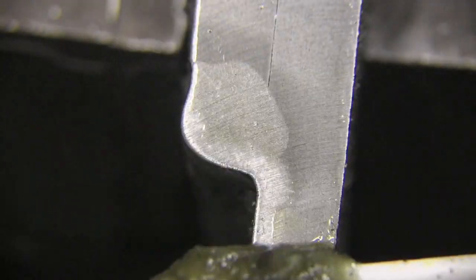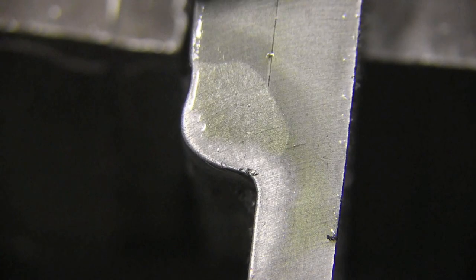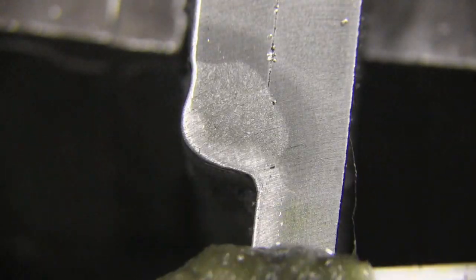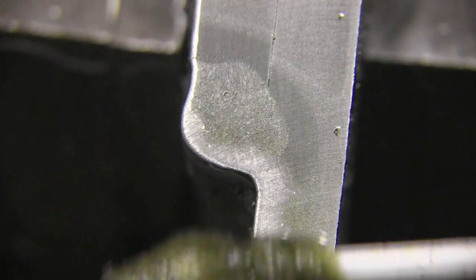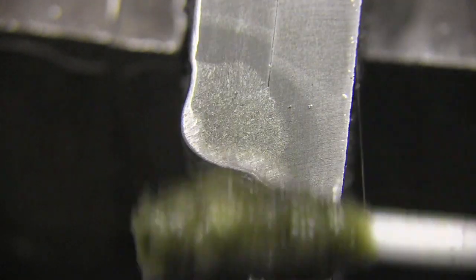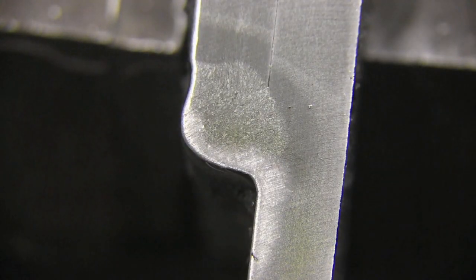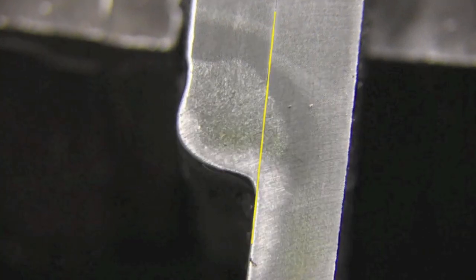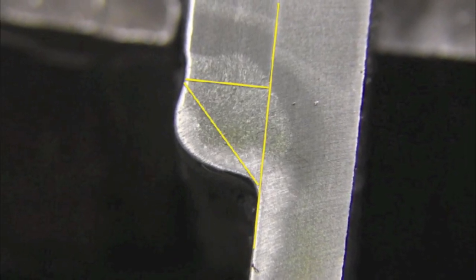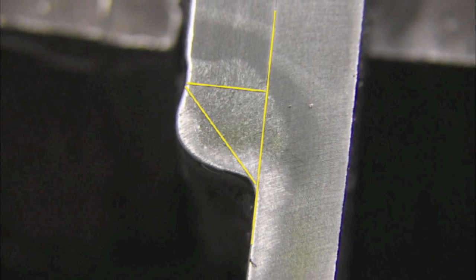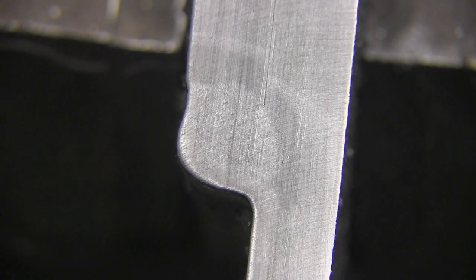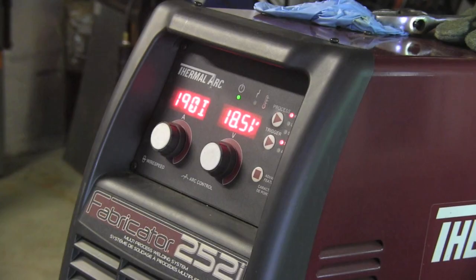Now, with not cleaning the mill scale at all, just a wipe down so it didn't have any oil on it, tremendous difference. Even at lower settings, that's a good nugget profile. Penetrated all the way into the root of the joint and then some, and didn't just lay flat against the metal. We don't have a braze profile here like we did on the downhill. So that's a lot of depth of fusion. Good penetration into the root. The only problem is the high crown. And once again, the high crown is not always a problem. It just can be if certain codes prohibit that or if an inspector doesn't like to see that.